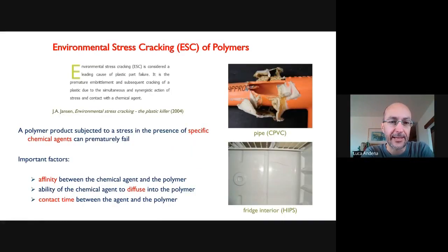What is environmental stress cracking? It's a well-known cause of failure for plastic products, which is caused by the simultaneous action of two factors: the presence of a mechanical stress, and at the same time, the influence of some kind of active medium. An important thing to point out is that the medium does not have to be chemically aggressive towards the material. So it's not actually degrading the material somehow. However, it can strongly decrease the fracture resistance of said material, thus leading to premature failure of a given product.